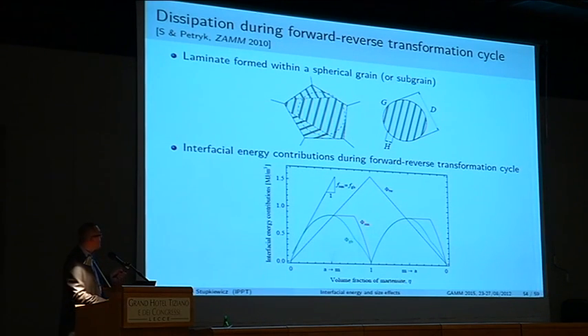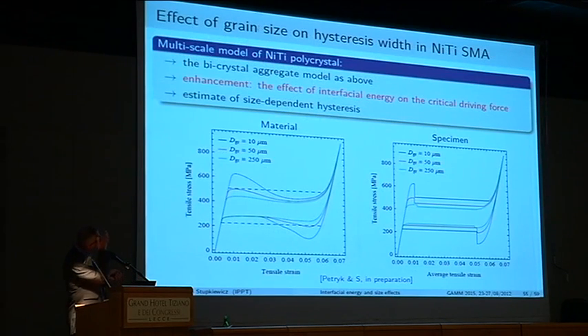Anyway, we want to enhance this model with the interfacial energy. So we consider this kind of spherical grain, for which we know how to estimate the elastic strain energy. We consider all the individual interfacial energy contributions that might appear in that system, and this is the result. So we have the material response of this kind, again depending on the grain size. The green would be the large grain, smaller effect, and the blue would be the smaller grain with a big effect of the interfacial energy. Of course, you see a severe softening here, so you don't expect to observe such a response in practice for an actual specimen. So we make a simple scenario taking the Maxwell line and localization criterion. This is just a sketch of how the actual response of a specimen might look.